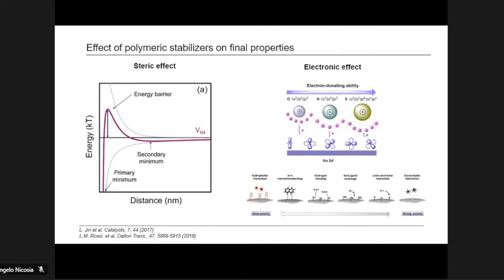The employment of a polymeric stabilizer has, first of all, a steric effect, to limit aggregation and improve stability, and therefore avoid a loss of their peculiar characteristics derived from the nanometer dimension. On the other hand, we have an electronic effect derived from the interaction between the polymer matrix and the surface of the metals. Therefore, we have a sort of modification of the charge density of the metal derived from the polymer presence, through different types of interaction, weak and strong.